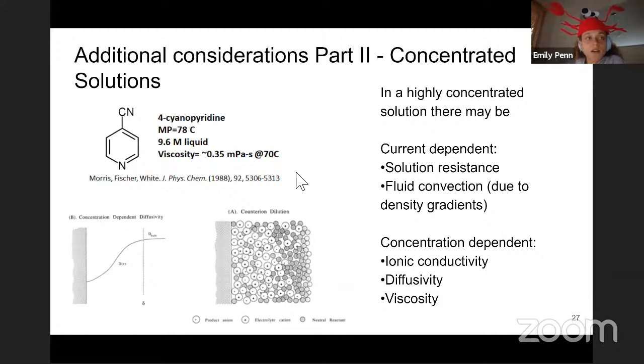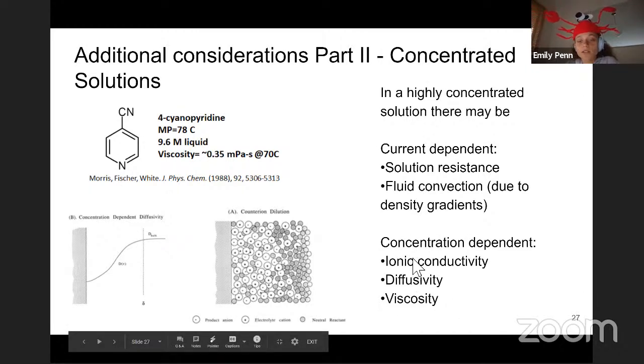Just another quick aside, all of the equations that we considered here have been derived for dilute solutions. So since we're looking at systems of liquid quinones that are highly concentrated, these don't quite fit the equations, and there are some other things that we need to consider. So in this paper, this group looked at a redox active organic liquid, a cyanopyridine, and found some other non-ideal scenarios that happen when you're doing voltammetry in an extremely concentrated liquid. So this liquid was almost 10 molar. And they found that different things like the solution resistance and the fluid convection are dependent on the current. And you can also have different factors which are normally considered constants that are then dependent on the concentration of your oxidized and reduced species.